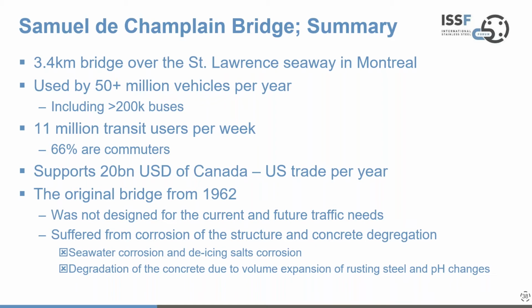And the degradation of concrete came from volume expansion of the rusting steel inside the concrete, because corroding steel increases in volume due to the volumetric expansion when iron combines with oxygen. And that also changes the pH as you get carbonation of the structure, which causes further degradation of the concrete. So that combination of having a seawater environment, using de-icing salts, and a lot of traffic over the bridge causes a lot of problems when you have a rusting product inside the concrete.